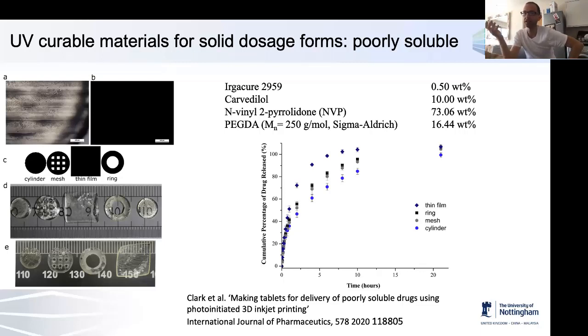Here, actually, we didn't get that, and you don't always get that because this is a swellable formulation and it's also an erodible formulation, and that does not necessarily align exactly to surface to volume calculations you might get out of a geometry. So you have to be a little bit careful when you're trying to get predictive quantities out of that kind of calculation.